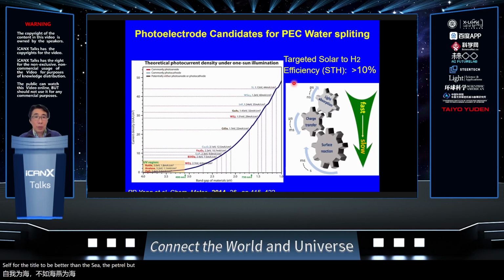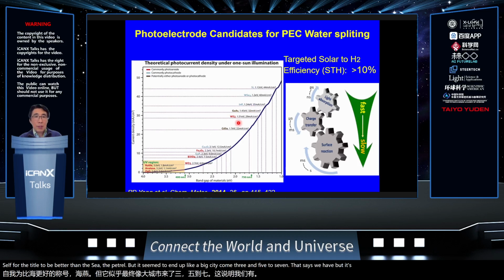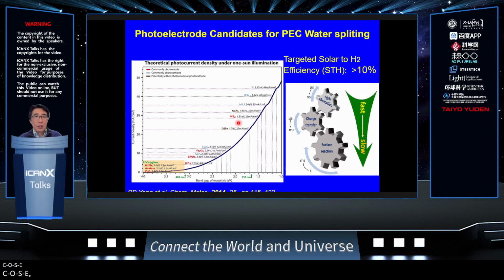For most of the photocathodes, they behave much better than the photoanodes. But for photocathodes, like silicon and III-V group semiconductors, they are quite expensive. They are also not very stable in certain conditions. And the most studied photocatalysts like TiO2 all belong to the photoanode. That's basically for the oxygen evolution process. This 4-electron reaction is also the bottleneck of the whole PEC system.